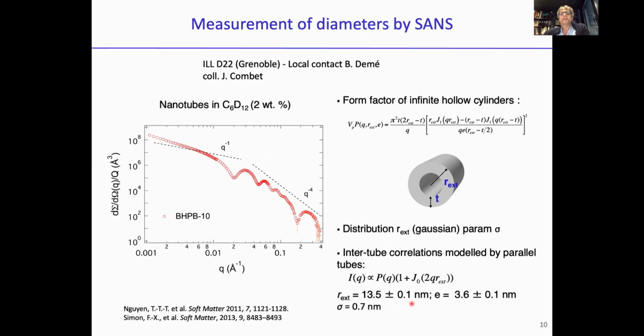And I will show you an example of what has been done in ILL on the neutron scattering. So we form the same nanotube, like I showed you before, but in a surrounding deuterated solvent, so that we have contrast between the deuterated solvent and the protonated objects. And this is the intensity that was scattered by these objects versus the transfer scattering vector, which is more or less proportional to the scattering angle.